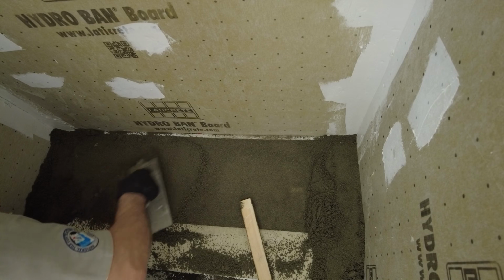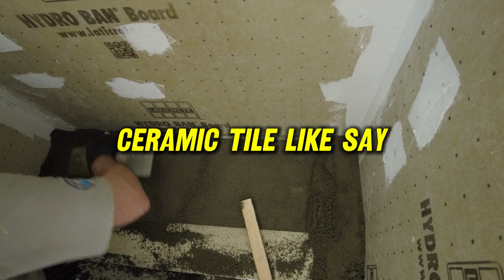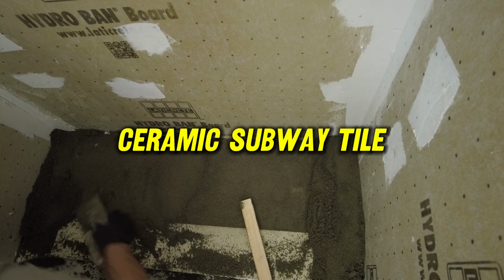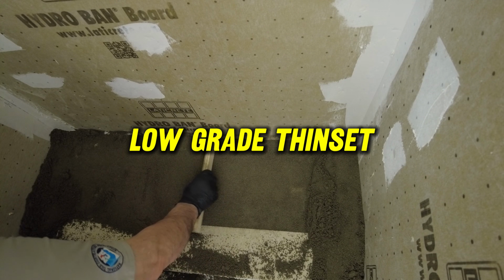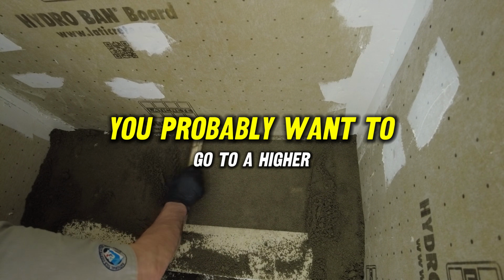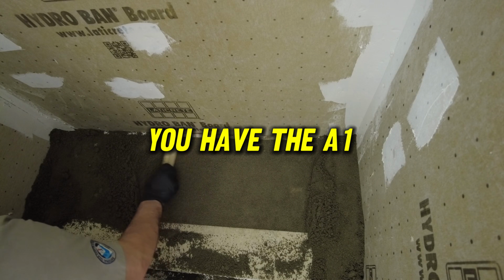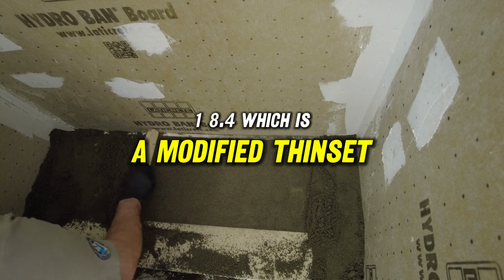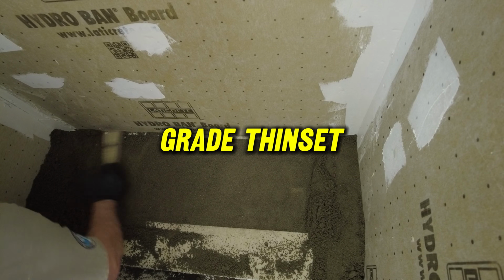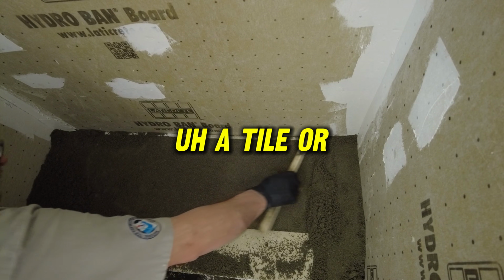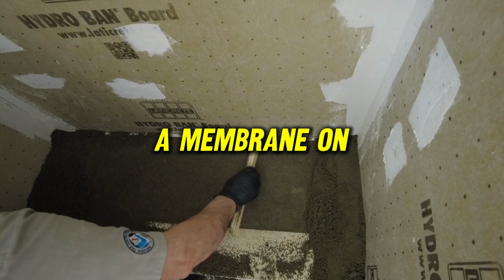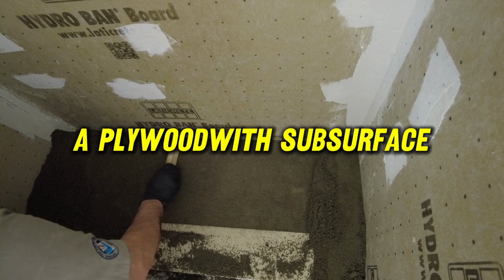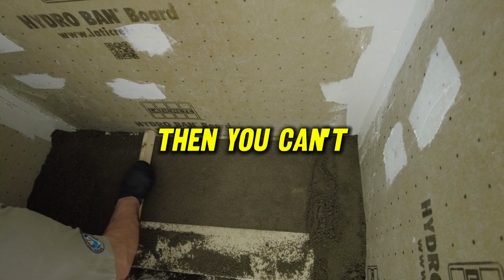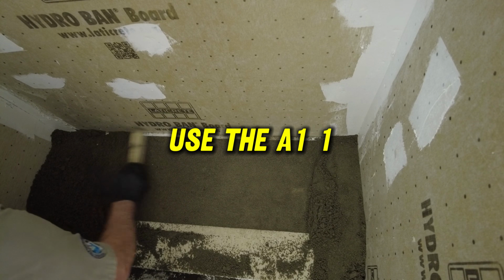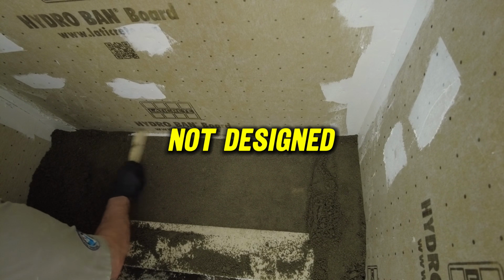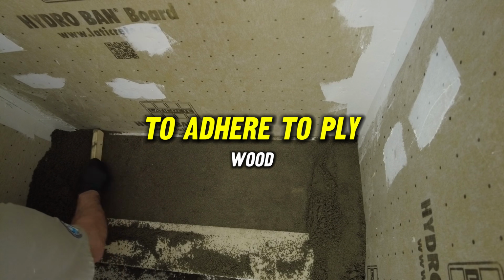If you're installing a ceramic tile, like say a ceramic subway tile, you could use a lower grade Thinset. If you're installing a porcelain tile, you probably want to go to a higher grade Thinset. You have the A118.4, which is a modified Thinset, but it's the lowest grade Thinset. If you're going to install a tile or a membrane on a plywood subsurface, then you can't use the A118.4. That is not designed to adhere to plywood.